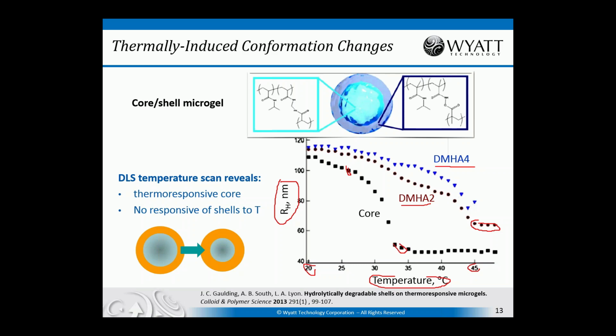And so this is a quick and easy way. You pop your solutions into a cuvette, put the cuvette into the detector, tell it to ramp the temperature. This probably took on the order of 10 to 15 minutes to run each one of these, and so it's a quick and easy way to measure these. One of the nice things about this measurement is that it's a very direct measurement. So another way to make these measurements, for instance, might be to use fluorescence or some other techniques, which are indirect measurements of the collapse of the shell. Here you're directly measuring an essential physical property, which is the size, and so you can see very directly what's happening to the particles as they go through this transition.